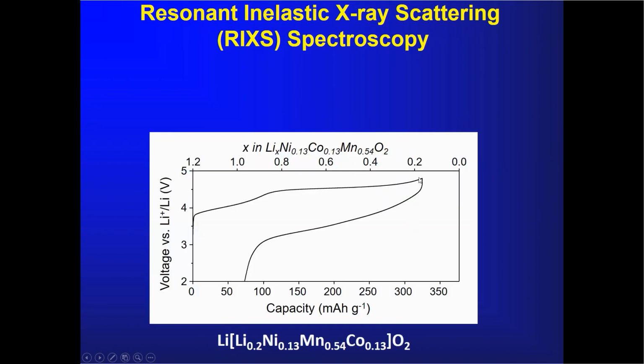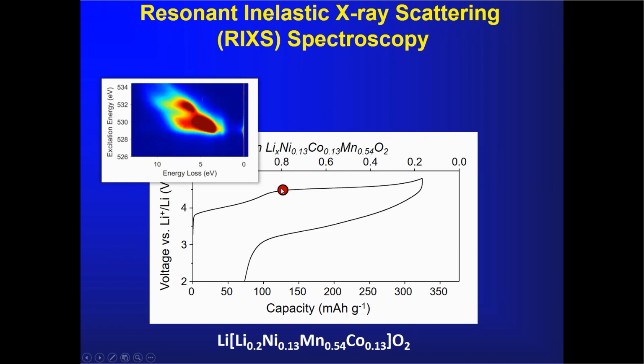So here's our charge and discharge curve again for our favored material, this lithium, nickel, cobalt, manganese material, the archetypal example, I think, of a layered lithium-rich material with excess capacity. And there's our plateau related to oxidation of oxide ions again. And I'm now going to show you this RIXS spectra collected at several key points along this curve. So here's the RIXS spectrum collected at the beginning of the plateau. This is the end of the normal transition metal process, where we're just entering the oxygen redox process, the oxide ion oxidation.